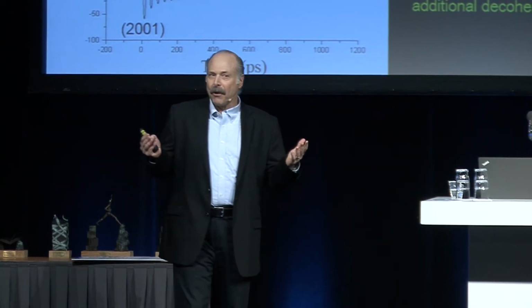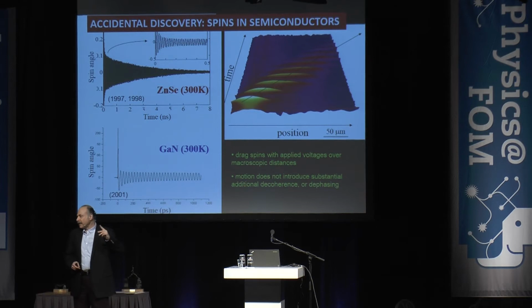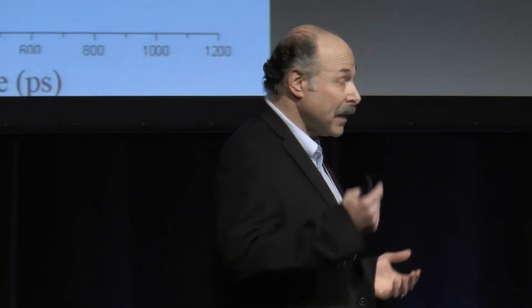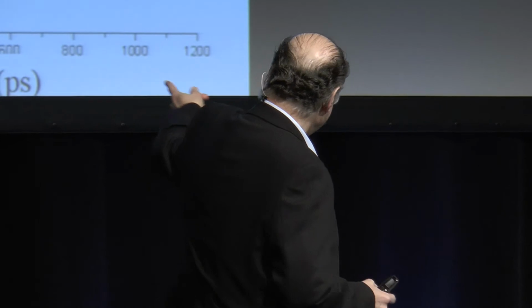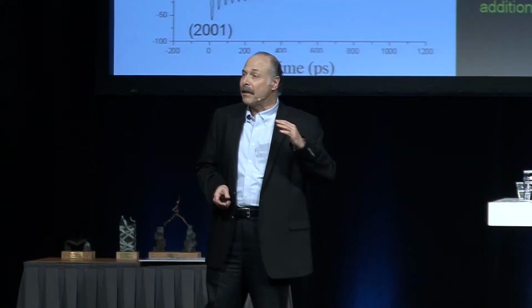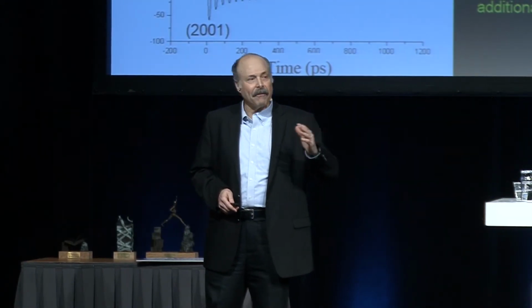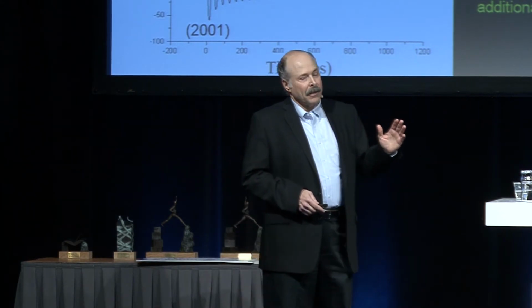Yeah, so gallium nitride is a very important technology material that's used a lot in solid state lighting. At this time, when gallium nitride was first being made, it was riddled with defects, threading dislocations. It was really, I think the technical word is really a crappy material. And so people weren't using it for much. But despite the fact that it was really filled with defects, it was able to generate and sustain extremely robust quantum coherence. A very big surprise. So it made us realize we still didn't understand very much about generating and playing with quantum states in just standard semiconductors, and it was a very exciting opportunity.